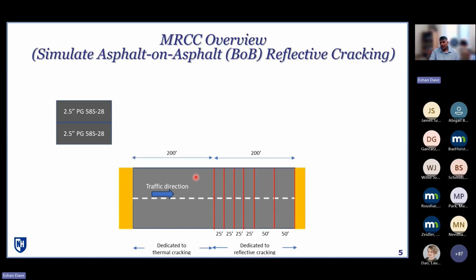So the way the study is designed, and again, it was really through the flexible team within NRRA as a group effort, everyone pitched in and provided feedback into designing these sections. The way these were built was initially building 5 inches of asphalt on top, in 2 lifts of 2.5 inches each. A standard MnDOT 58S-28 mixture was used. All the mixtures in this study are 12.5 millimeter, or half inch. So that's the mixture that was used, placed in 2 different lifts.